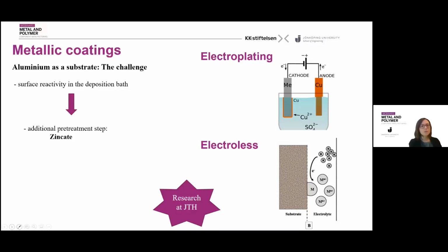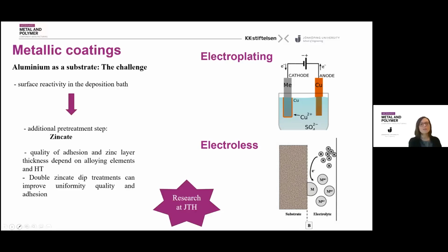When you work with aluminum, you should apply a pre-treatment, most commonly a zincate pre-treatment, that passivates the surface and puts some zinc on it so you can protect the aluminum while immersing it in this electrodeposition bath, so that you are building a strong metallic layer on it.